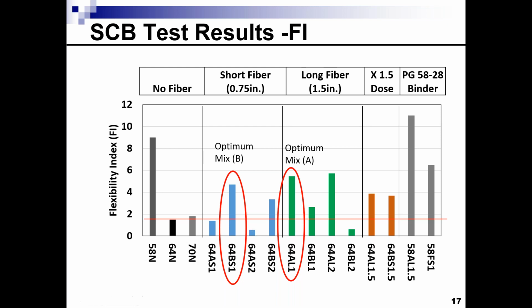The first thing that we can see is that the addition of the fiber seems to enhance the flexibility index. This might suggest that it also enhances the cracking resistance of the mixes. If we compare here, the optimal case is where, for type B, it is the short fiber, which is 19 millimeter, at the dosage recommended by the manufacturer. And again, as you can see, it enhanced the cracking resistance as compared to the non-reinforced.